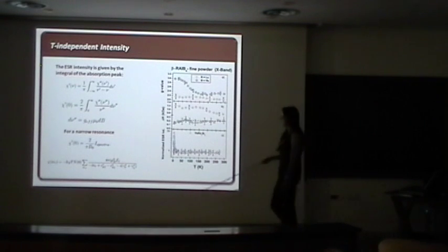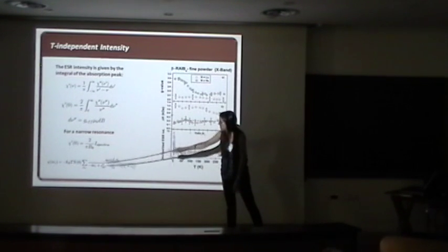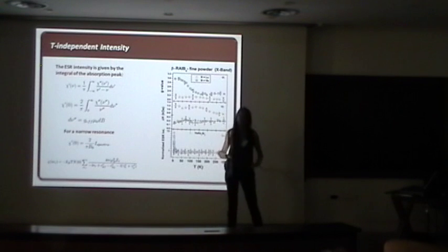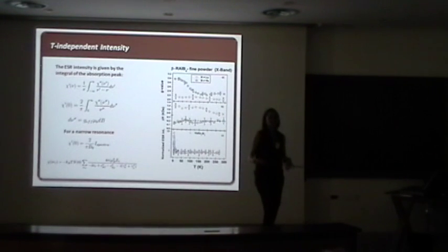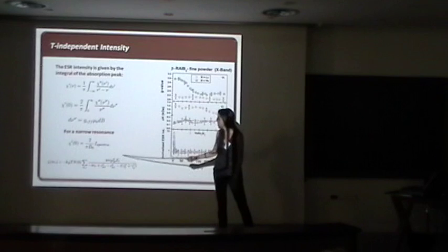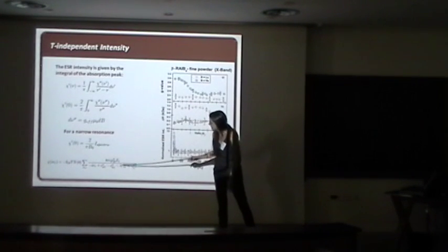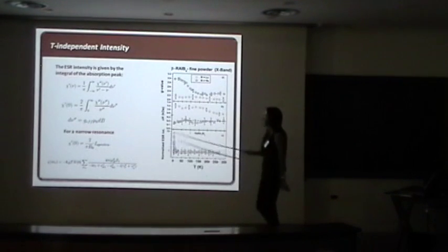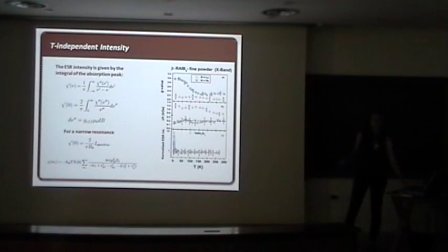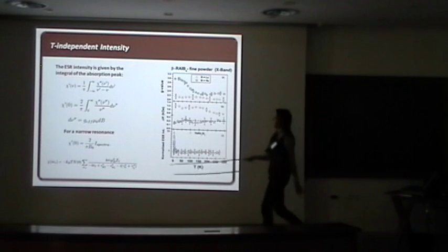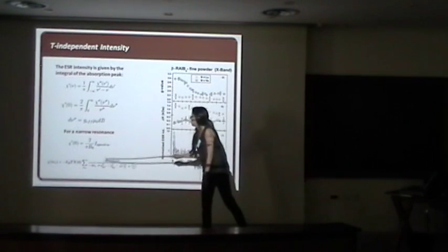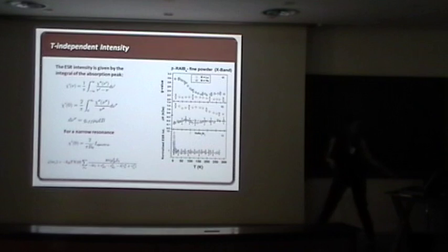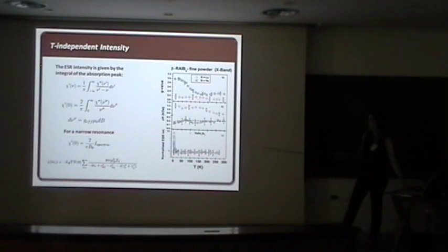And if I notice that this is a susceptibility of the conduction electrons, I would not expect it to renormalize, because it has this renormalized factor here, and these star quantities all have a Z factor on them. So essentially, if I analyze the static term, I don't have any renormalization of this. So it explains why I have this temperature independence of the intensity.